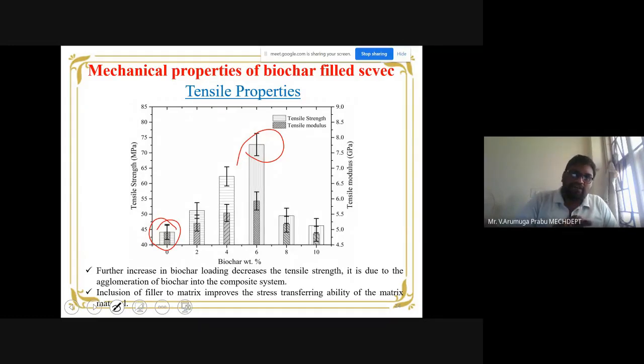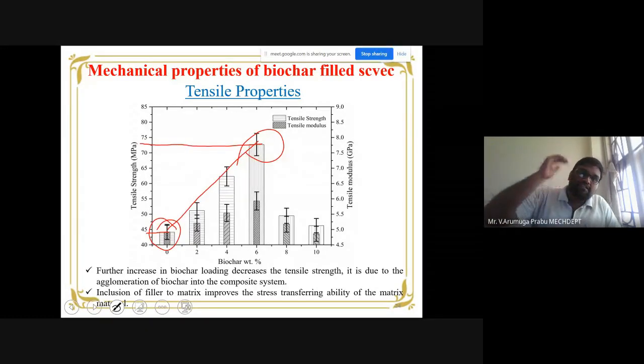Only Sansevieria fiber and the vinyl ester. So its strength is nearly around 45 megapascal. On the other hand, with the addition of biochar, especially 6%, you see how much it increased the tensile strength. It touches nearly 75. So that much high strength the addition of biochar yields.